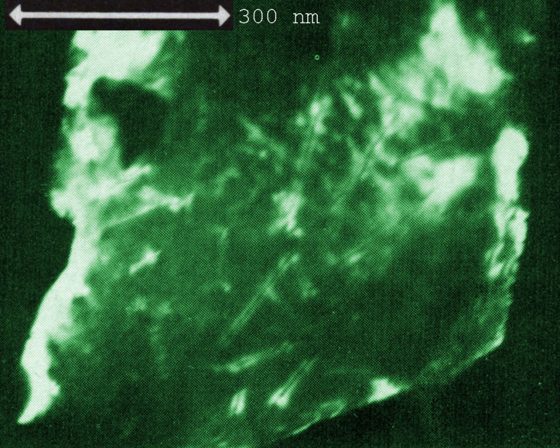Ion tracks can be selectively etched in many insulating solids, leading to cones or cylinders, down to 8 nanometers in diameter. Etched track cylinders can be used as filters, Coulter counter microchannels, be modified with monolayers, or be filled by electroplating. Ion track technology has been developed to fill certain niche areas where conventional nanolithography fails, including direct shaping of radiation-resistant minerals, glasses and polymers,